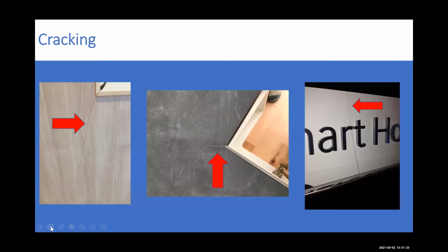If we look at the next screen, there are a few different examples of cracking here. They can be from acclimatization. We can have cupping happening here. In my opinion, these first two are stress fractures, because they're inside corners and they haven't been radiused properly. The one on the right is in a frame. It could be that they didn't file the edges properly, as Robin talked about, and so one of those tiny hairline cracks was allowed to go. And if there was any torquing on that sign, it would just snap.